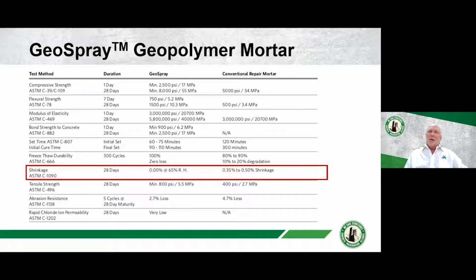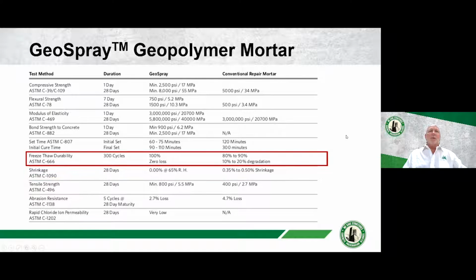Shrinkage, again, because the water is not part of the chemical reaction, the geopolymer material, actually it shows here 0 shrinkage. I've been in the concrete business for too long to even be able to say the words 0 shrinkage, but the shrinkages are very, very minimal. So if you think that you're going to be lining a culvert that's somewhere between 50 and 200 feet long, if you can put a material in there that doesn't shrink, then you're going to reduce significantly or eliminate the possible cracking. Freeze-thaw durability, again, because the material is so dense, it doesn't allow moisture to penetrate.